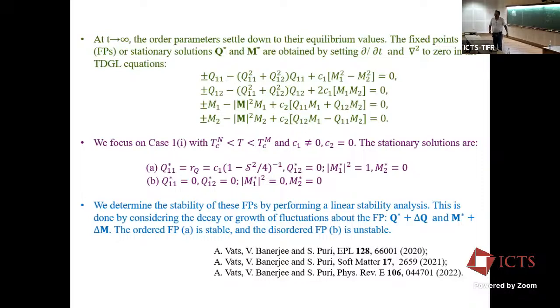Yes, you had a question there? I'm just showing it for a 2D system for simplicity. Exactly the same formulation works for a 3D system. The growth laws would be the same, as a matter of fact, because these non-conserved order parameters are very dull in that they always give this diffusive power law growth. At most, you can have a logarithmic correction in some cases. Invariably, it's square root of t.